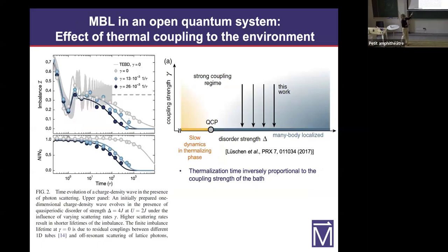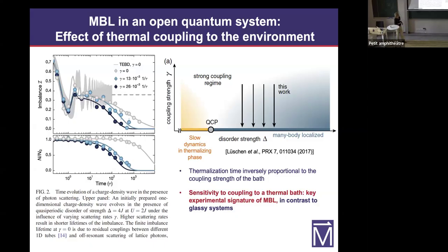I also wanted to mention that they investigated in this system, these ultra-cold atoms, the effect of the coupling to the bath. They could not reduce it further, but they were able to increase it. So when they do this on purpose, they found that the system does indeed thermalize much faster when the coupling to the rest of the world is increased. And in fact, this strong sensitivity of MBL to coupling to a thermal bath is a key experimental signature of MBL. And this is in contrast to glassy systems, which are robust with respect to the coupling to the environment.